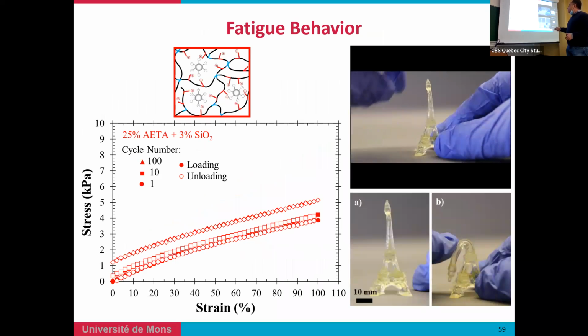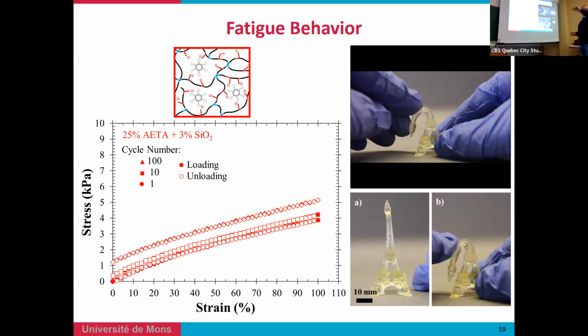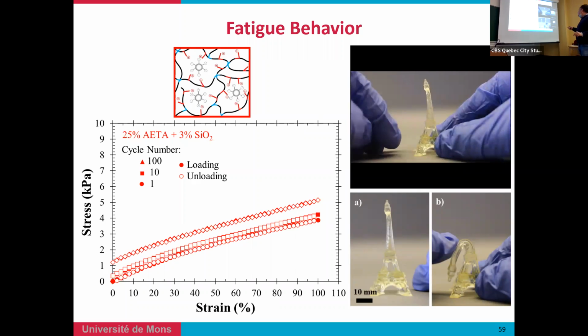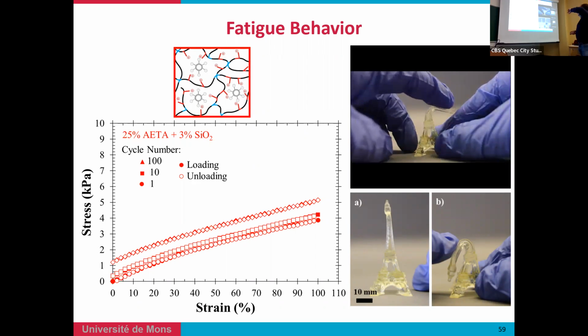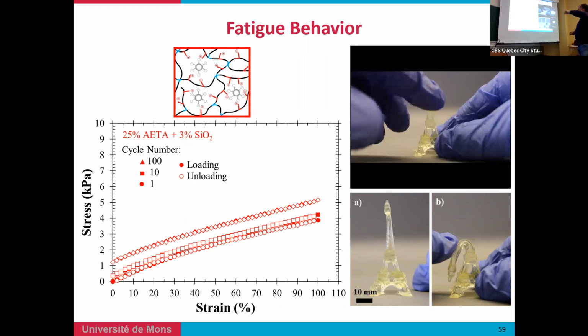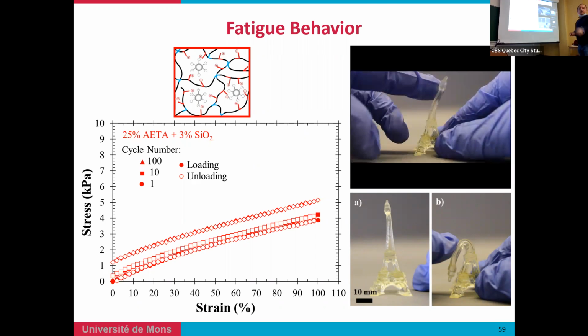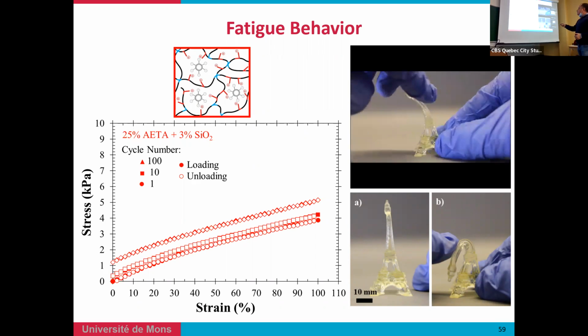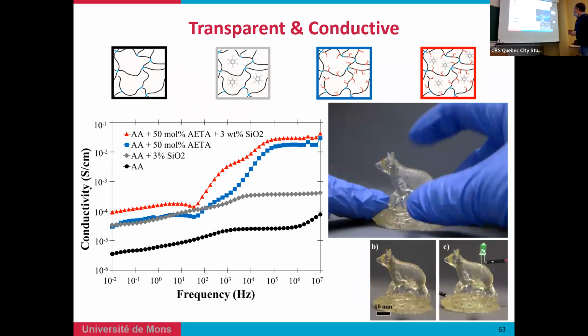So instead of showing a lot of curves, you can see on the video that with your finger you can deform the samples - in this case an Eiffel Tower shape - in different directions, and you can maintain the shape and do that several times. This is what you can obtain from this curve strand.